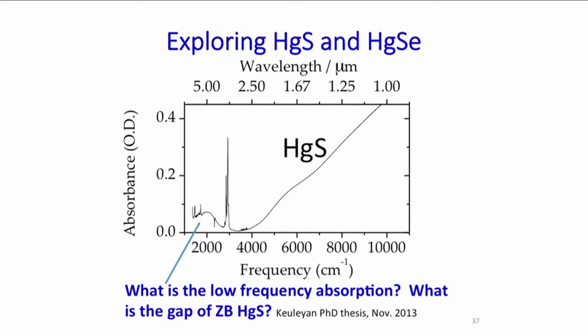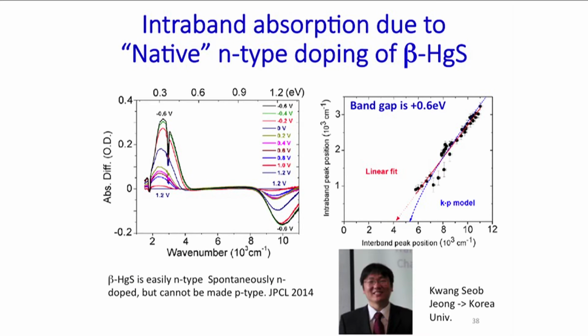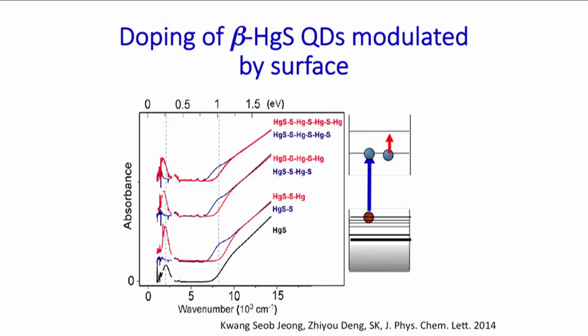And there were a number of possibilities, but eventually we found that this was what we were looking for 10 years earlier, which was this intraband transition of naturally doped nanoparticles. And so it turns out that this mercury sulfide is natively doped, as it is, in air. It has, for the right size, just 2 electrons in that state. Not only that, but we can change the number of electrons by changing the environment. And so that was a surprise, but it shouldn't have been.